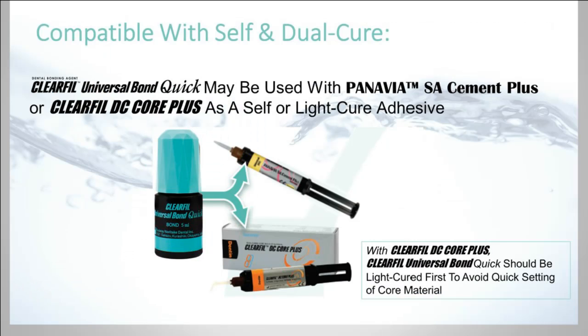And so you bring it down in there. You can use it with either of these materials. It'll make them go a little quicker. With the Clearfill DC Core Plus, Clearfill Universal Bond Quick should be light cured first to avoid quick setting of the core material. So that's why we light cure down in that post space beforehand, because we don't want it curing the DC Core Plus even quicker. That's a dual cure material, light cures and it auto cures. And so it's ideal for putting a post in, and then as you build it up, that's your core as well. It's not only the cement, but it's the core buildup.